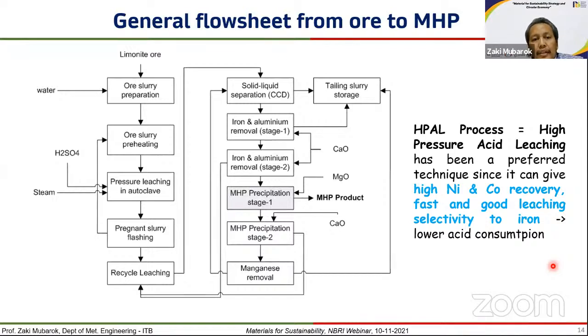And in general, the flow sheet from ore to MHP is as follows. Starting with slurry preparation, preheating, leaching, and then recycle leaching, solid liquid separation, iron removal in 2 stages, and MHP precipitation in 2 stages. And from the first stage, recover as the product. And high pressure acid leaching has been a preferred method, since it can give high nickel and cobalt recoveries, fast leaching and good selectivity to iron. Therefore it results in lower acid consumption. As far as I know, the plan for several new processing plants for producing MHP in Indonesia also utilize this kind of technology, HPAL, although it requires quite high investment cost.